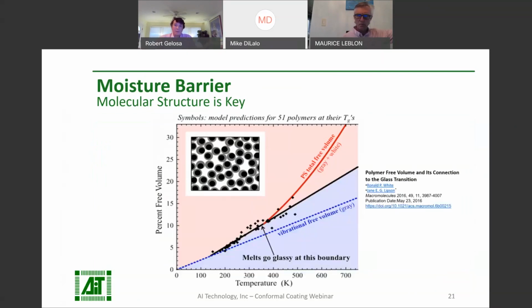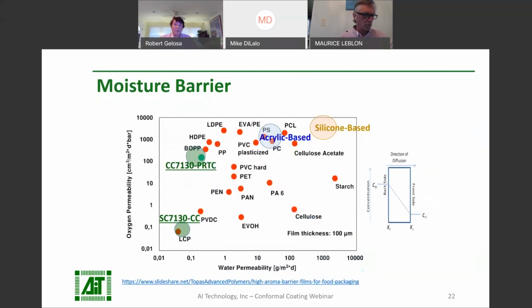In many polymer coatings with low TG, or glass transition temperature, such as silicone, the free volume is high. Polymer coatings demonstrate a greater increase in free volume and pore size as the temperature increases above TG. One of the most significant challenges in the molecular structural engineering of conformal coatings is creating a flexible, low TG conformal coating with small free space and pore size. This is exactly what AIT did in creating our new conformal coatings CC7130 PRTC and SC7130 CC.